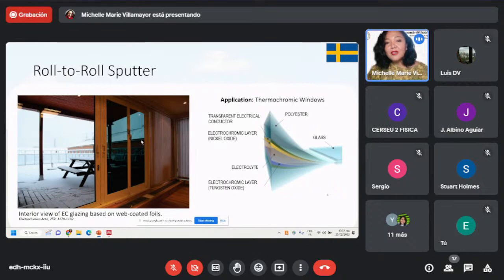So we actually have a polyester which is deposited with an electrochromic layer, nickel oxide, and then we also get another polyester where we deposit tungsten oxide. And then in between these two polyesters with metal oxide deposit is an electrolyte. Once these two are sandwiched together, we put it inside a glass. And this glass now becomes our window.